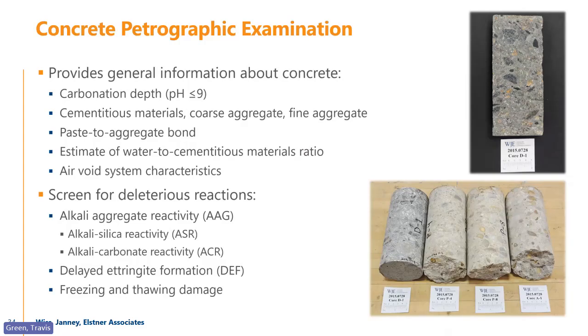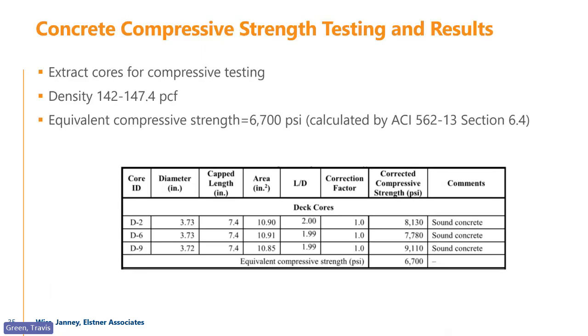We can estimate water to cement ratio. We can look at void characteristics, right? Void spacing and the amount of entrained or entrapped air. In this area, we'll also look for alkali ASR type degradation. I don't think most of our structures will see DEF. A lot of times that's associated with either mass concrete or precast type work that's been cured at high temperatures, also freeze-thaw damage. So it may not necessarily go strictly into the service life model, but we often do it to get a better sense of what's going on.